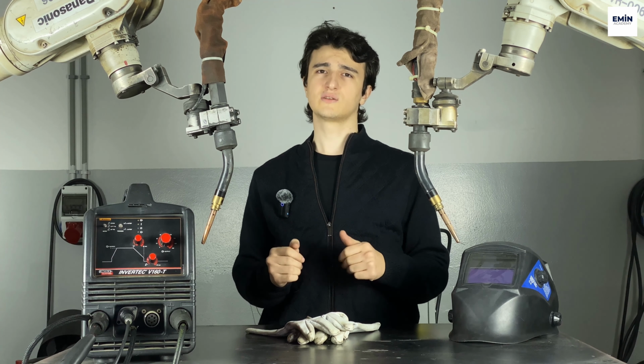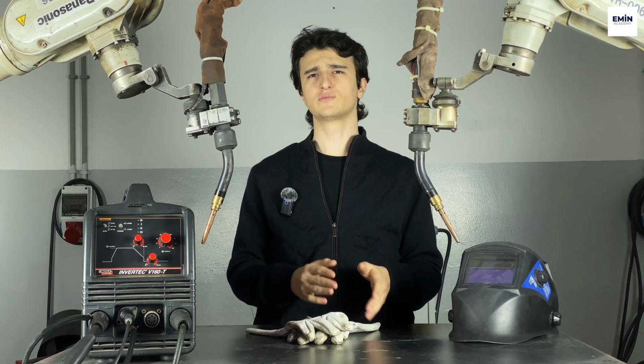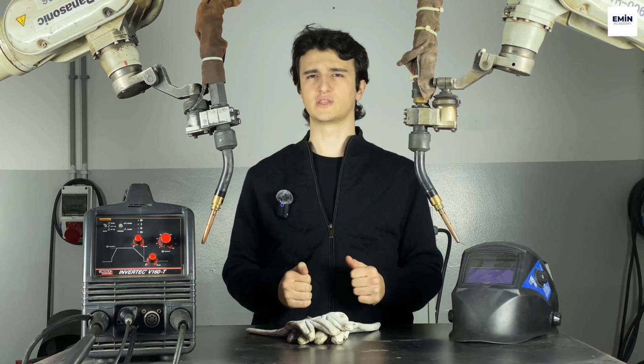The most ideal balance setting for aluminum welding should be 70 to 75% electrode negative. In this range, you get sufficient oxide cleaning, solid penetration, a stable arc, and a long tungsten life.